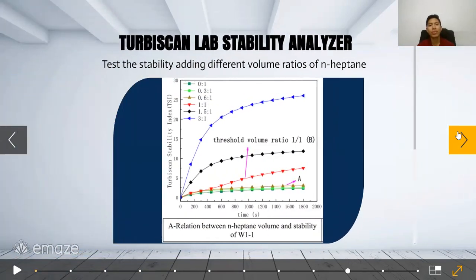For that reason, the same five samples were analyzed using a Turbiscan lab stability analyzer. It was used to test the stability of the crude oil by adding different volume ratios of n-heptane and measuring the transmission ratio and the Turbiscan stability index of the mixture. In this process, it is important to use n-heptane of a high percent of purity. I read that 99.999% purity was used, so it's very high.